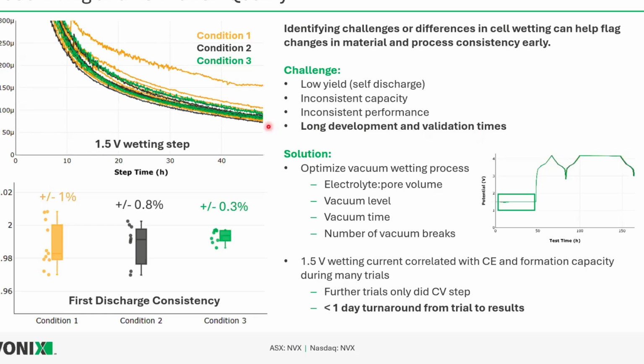When we were trying to optimize our vacuum staging protocol for injecting electrolyte and then pulling vacuum for certain periods or vacuum levels, we used UHPC just in this very first step of formation, where we do a 1.5 volt voltage hold and measure and monitor the current supplied to the cell to maintain that voltage. The more consistent that current is, and the lower at the end of that voltage hold, means there's more consistent wetting, and there's not continued wetting of new material within the cell.